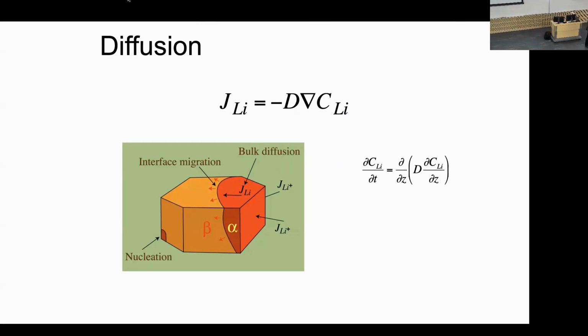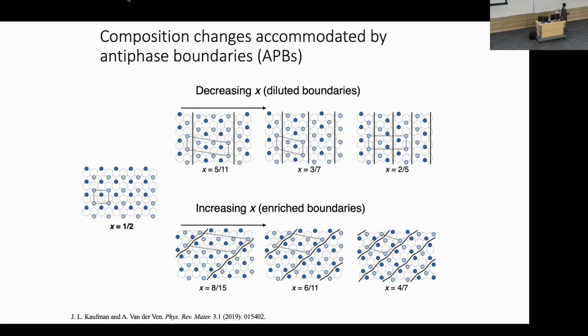And the reason that this is important, and unfortunately I probably won't be able to get to it, is, I mean, it's very interesting, but it actually has important consequences for diffusion. It turns out that the antiphase boundaries are actually crucial to mediate diffusion. And it's not the usual mechanism of atoms exchanging with vacancies in these sodium compounds. Instead, it's actually the motion of antiphase boundaries themselves going through the crystal. So the diffusion is not a vacancy mechanism, rather it's waves of these antiphase boundaries going through the crystal, and that's how you can accommodate composition changes. It turns out that the kinetics of moving these antiphase boundaries with a kink mechanism and extension is much more facile than moving individual sodium atoms by exchanging with vacancies.